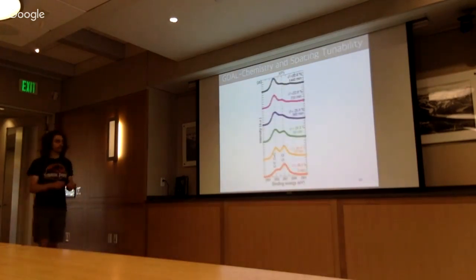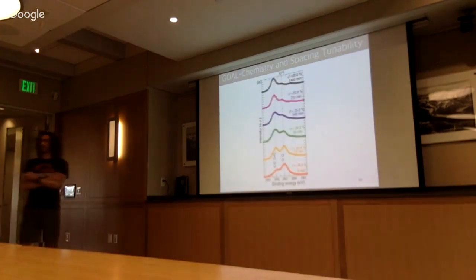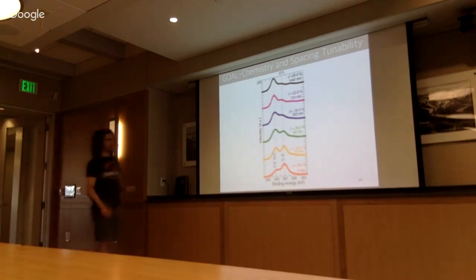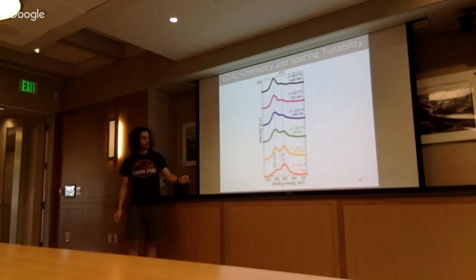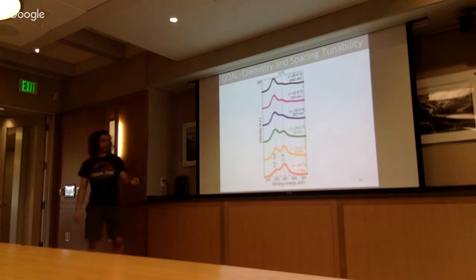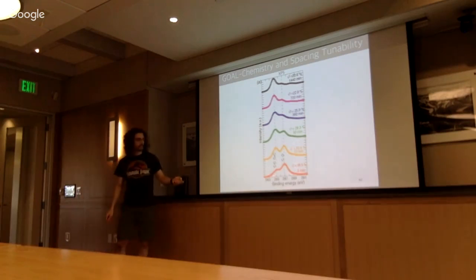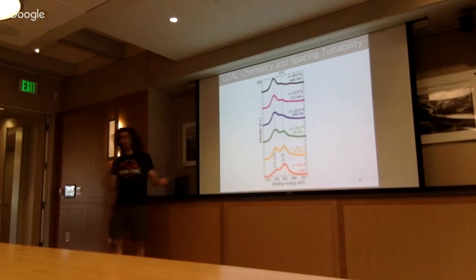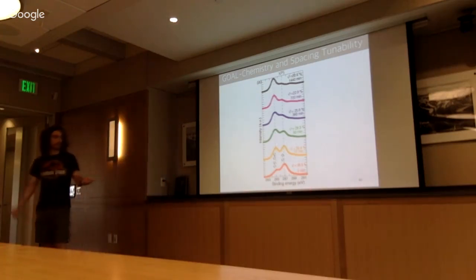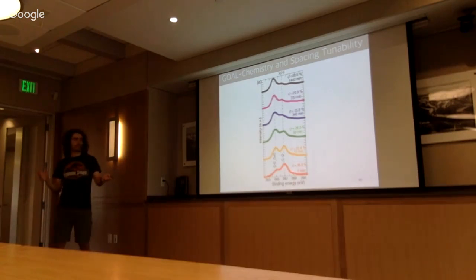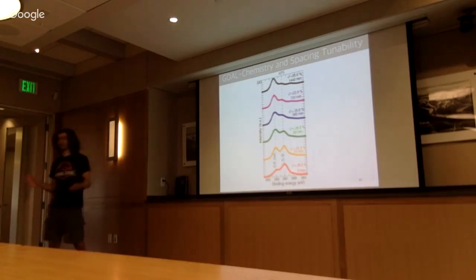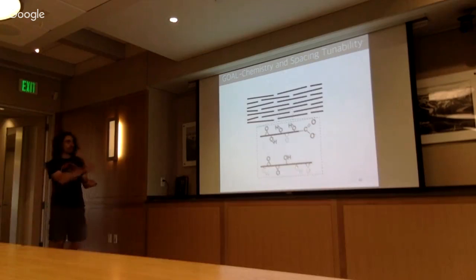So again, what we did for the first time, we exposed graphene oxide in vacuum to UV irradiation. So what is happening here? Here I'm increasing the irradiation time from 0 minutes to basically 1400 minutes. As you can see, the C1s XPS spectra is modified, right? And from this, you can infer that the oxygen percentage is changing from 35% to 20%. So what is happening? We're basically removing some of these oxygen functionalities.